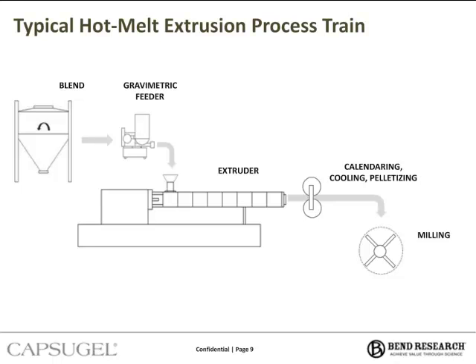So this slide shows a typical hot melt extrusion process train. And there are a lot of permutations to this, but this is a very simplistic way to look at this. And in general, what we would do is you have a blend, and that's a polymer and a drug in the simplest of cases. And that's fed either gravimetrically or volumetrically to an extruder. And then the extrudate is calendared, cooled, and pelletized, and then finally milled.